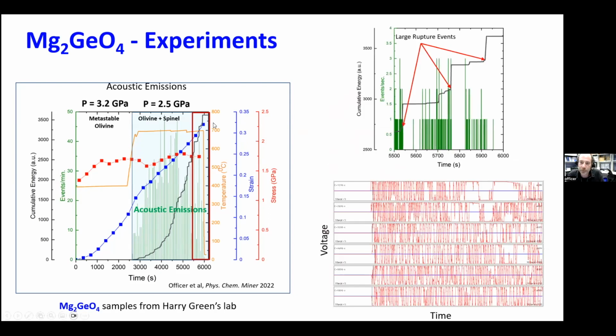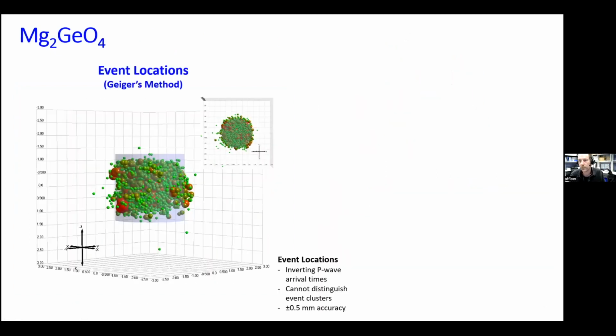If you look at the end of the experiment here, the last maybe 15 minutes, what you see is you'll build up a bunch of acoustic events, and then all of a sudden you'll have a huge event like this that completely saturates the entire trace. So you have this big jump, and then nothing happens for about 2 minutes. Usually you're getting acoustic signals every 3 seconds on average. Nothing happens in this period. Then you start to have some more acoustic events, and then you get another one of these huge events where you generate a fault in the sample, and then nothing happens, a few events, and this will happen a few times towards the end of the experiment.